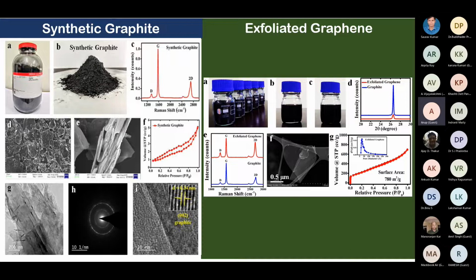Then image D, which you are seeing here, is the X-ray diffraction image. In this, the blue one is for the graphite and the red one is the exfoliated graphene. What we found from these two is a sharp decrease in the intensity of the exfoliated graphene. And please mark here on the Y scale, it is not an arbitrary unit. It is the actual intensity we got from the instrument. So the sharp decrease in intensity means definitely the exfoliation has taken place.